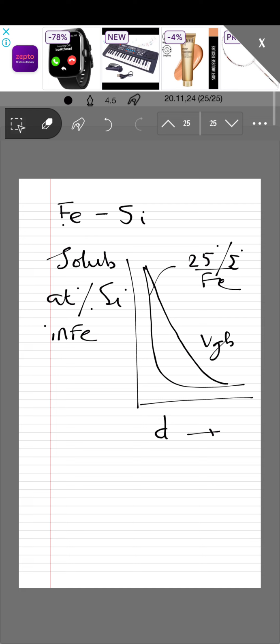So this grain size is 20 nanometers. So one can see that there is much less solubility until this threshold grain size has been reached. So till the size is 20 nanometer, there is almost zero solubility or next to negligible solubility. As soon as the grain size decreases beyond this 20 nanometer size, solubility increases greatly.